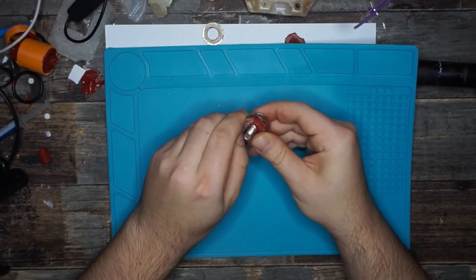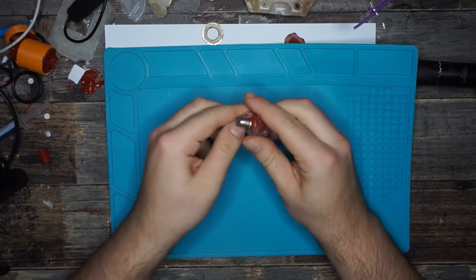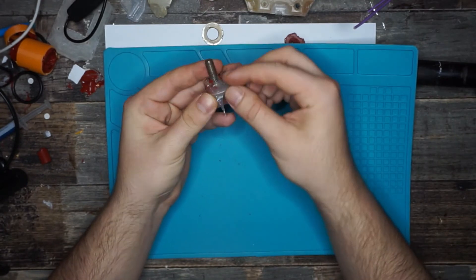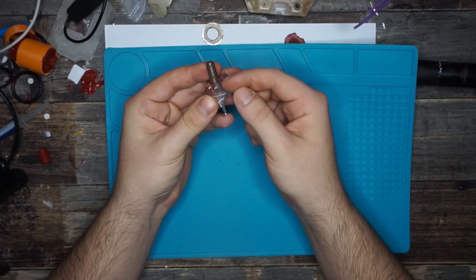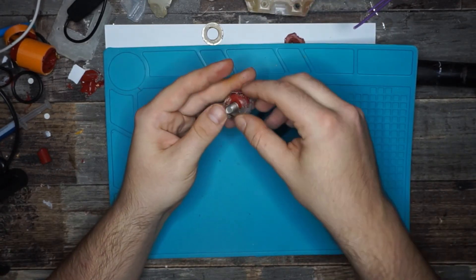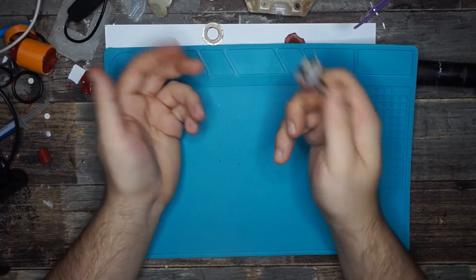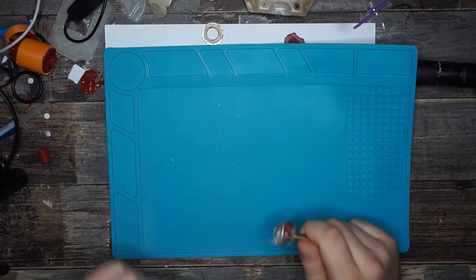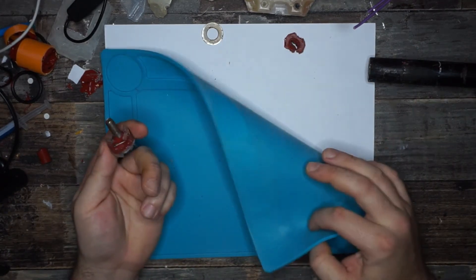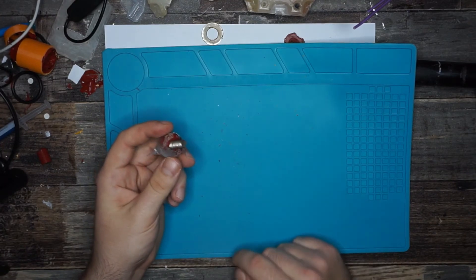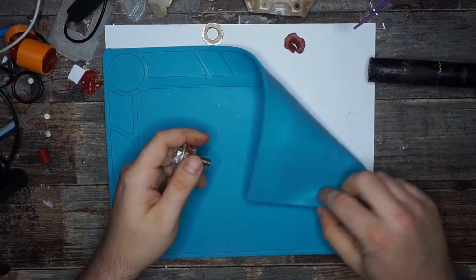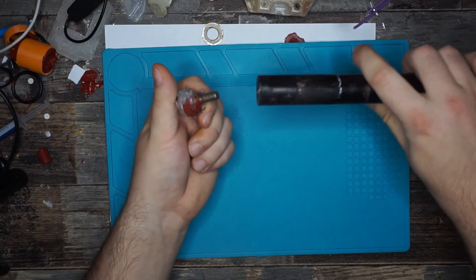Maybe it's holding up better to the pressure. But actually, I think the baffles were working fine. The main problem was that I was pressing them into the heating block at a slightly wrong angle, and then one side got mangled between the piston and the cylinder and began to rip off. Let's see if this stuff is actually a good material for this. I will cut out some baffles from this, and then we will try again, because right now I can't use my machine.